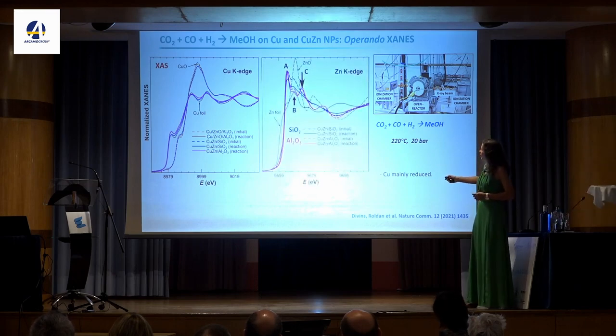Now, if you look at the zinc data, this is very interesting, because now we can follow the zinc, because it's not part of the bulk support, and we can follow the transformation. And so if you look at the data in blue, this is the copper zinc particles on silica. And you see these two peaks here, and you see that it looks very different from any normal zinc oxide structure that you could find. So the zinc oxide in these nanoparticles is highly disordered.